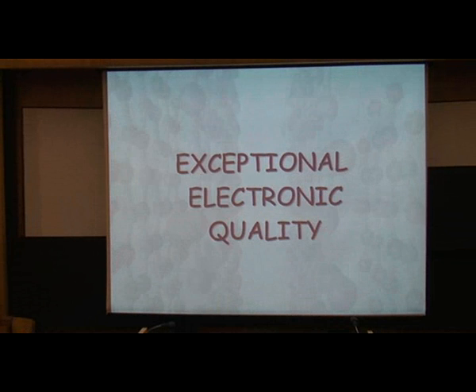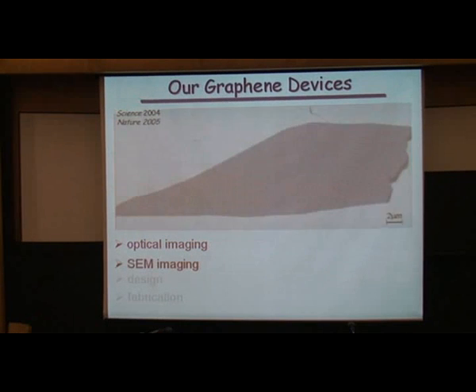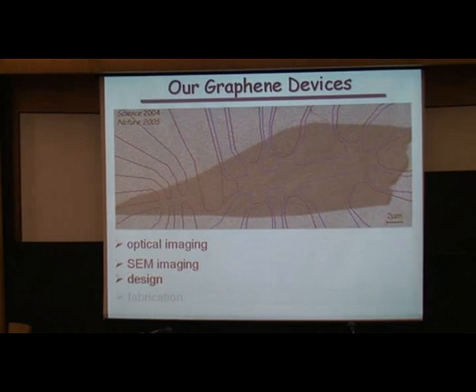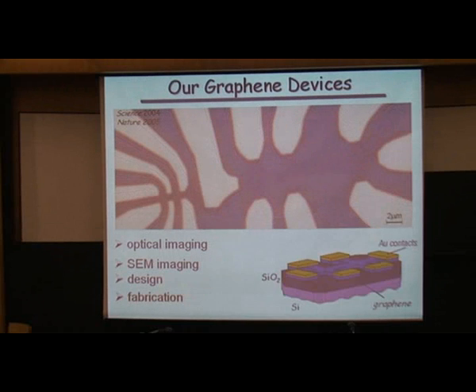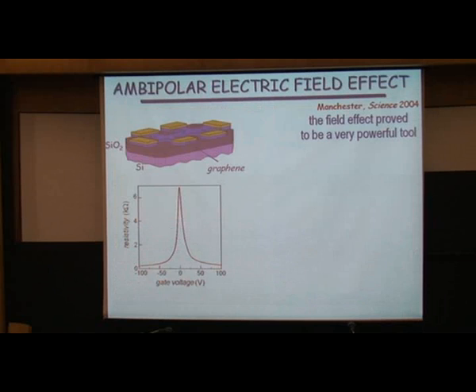The biggest subject, the most mature subject, is actually the electronic properties of graphene, and it will take most of my talk. In the very first studies we did the following. We not only observed those flakes that you can isolate, which is not that important. More important is that we made devices out of those flakes and started measuring their properties, and eventual devices look like that. Many contacts, and you can measure Hall voltage, you can put in magnetic field, different temperatures, resistivity, and so on.